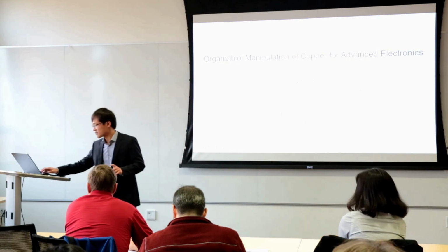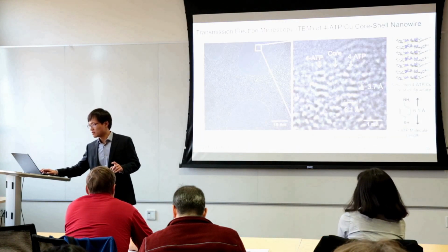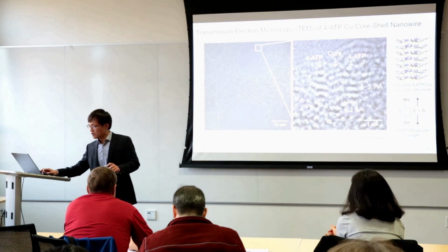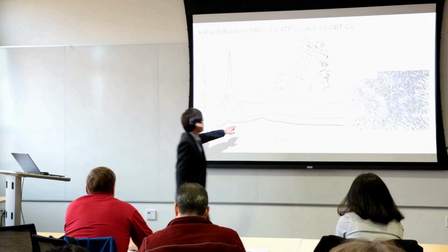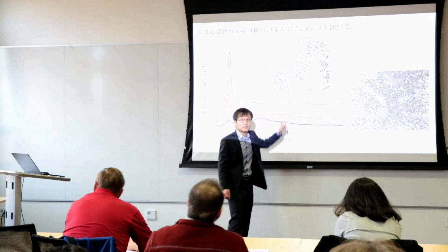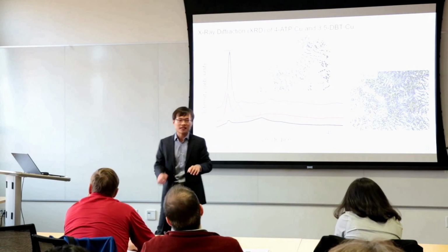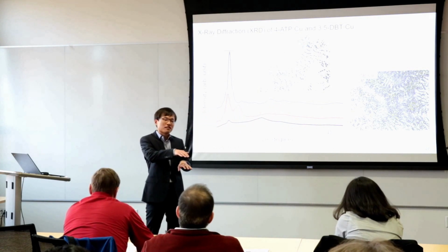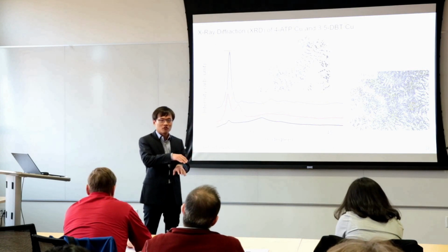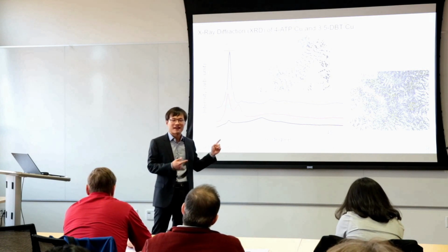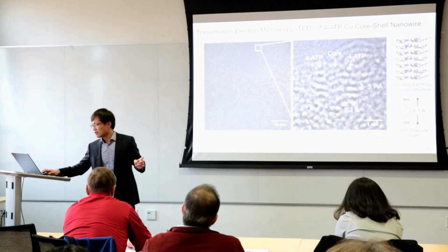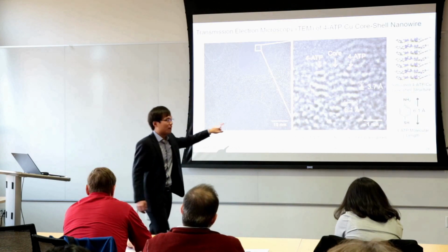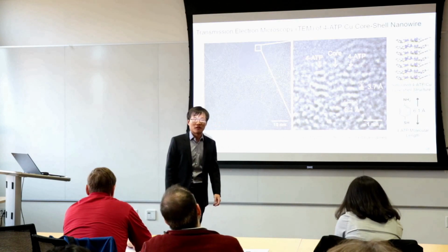And it also matches with the peaks from XRD as well, as you mentioned. In fact, if you look at this broad peak over here, between 3.2 and 3.9, that's exactly the pi-stack distance between aromatic rings. We in fact do have a correlation between XRD as well as our TEM image shown here.